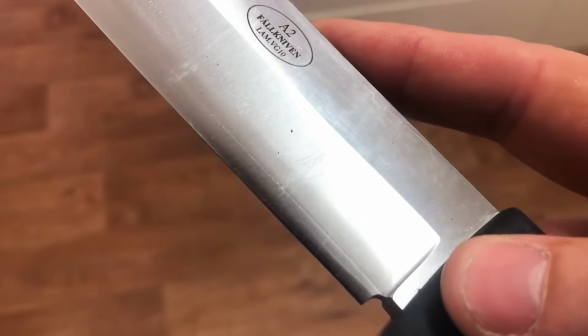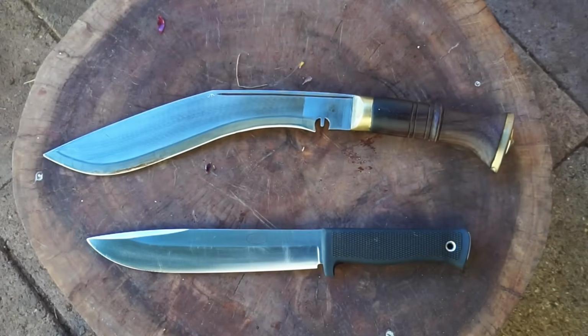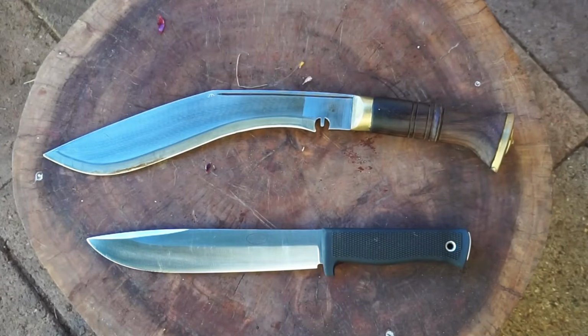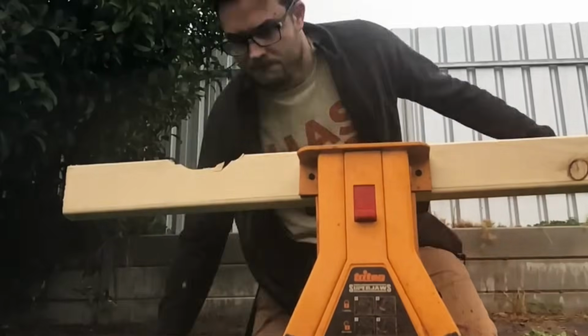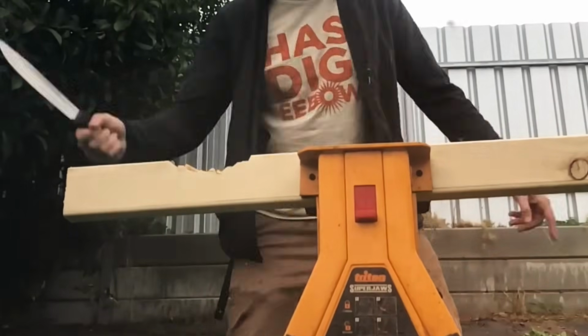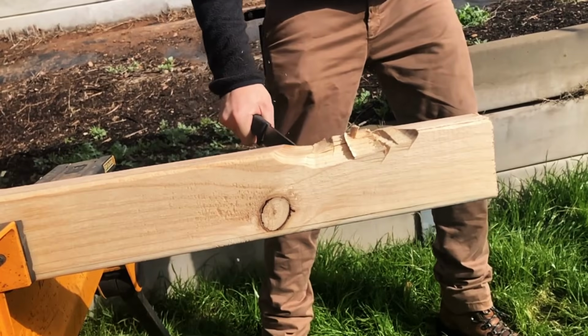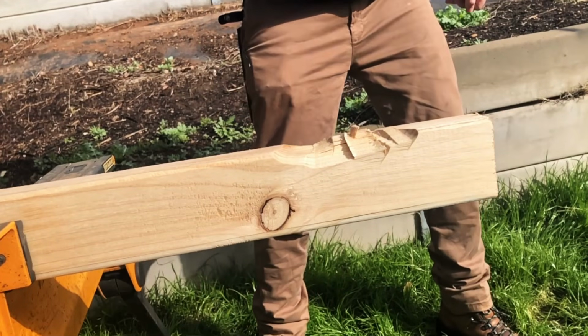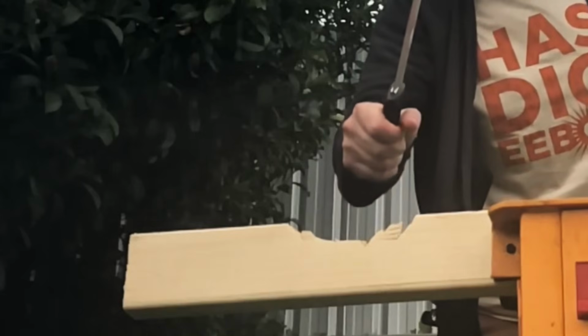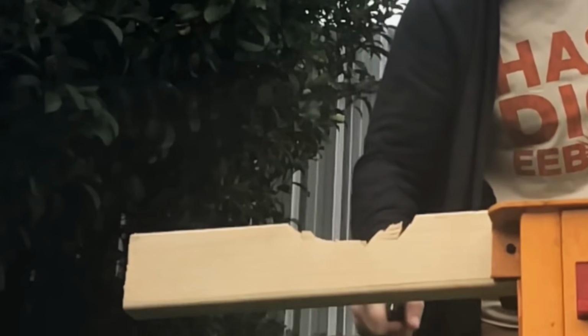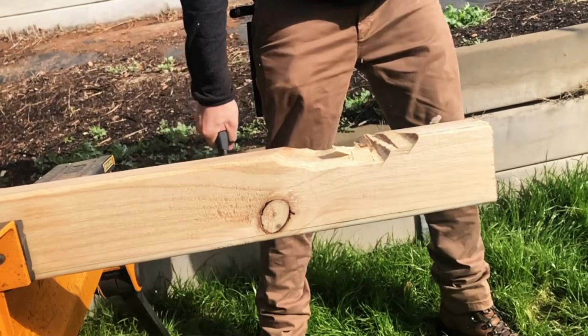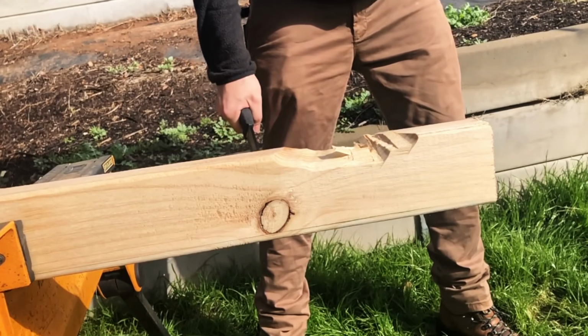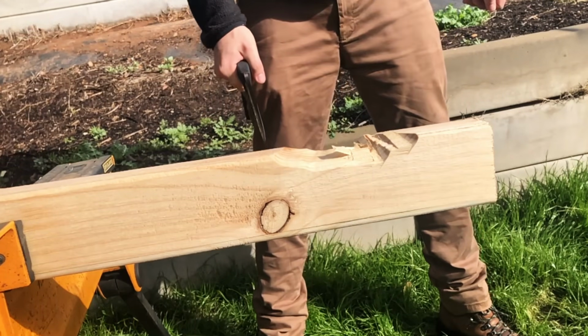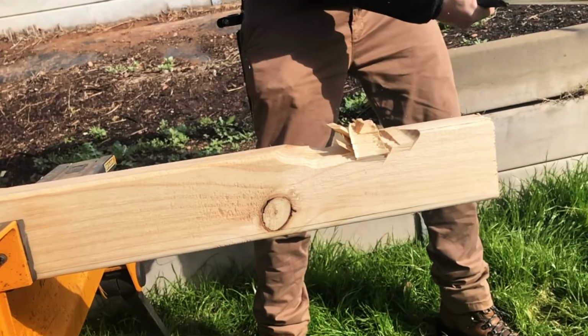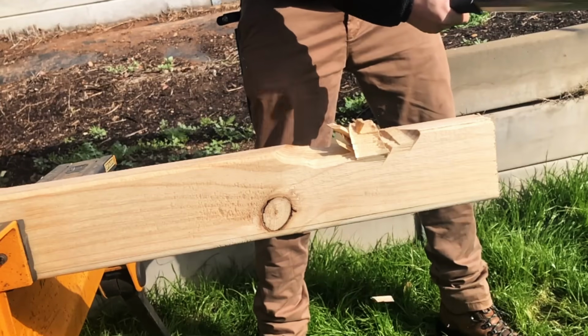$390. That is a number that makes the nail chop test result important beyond this video. Sight index equals 6.1. If you actually want a chopper, go with the ESEE Junglas. It uses 1095 carbon steel, which is tougher and easier to sharpen than VG10, and the nail chop test demonstrated exactly why that recommendation exists. VG10 at 59 HRC, while providing exceptional edge retention, carries a carbide structure that is more vulnerable to the specific impact plus lateral combination that the nail chop creates than the tougher 1095 and CPM steels lower in this ranking.